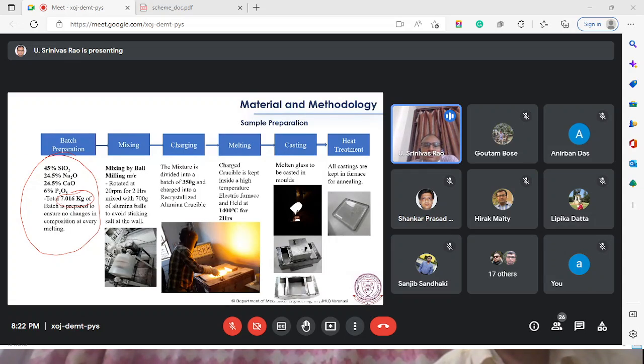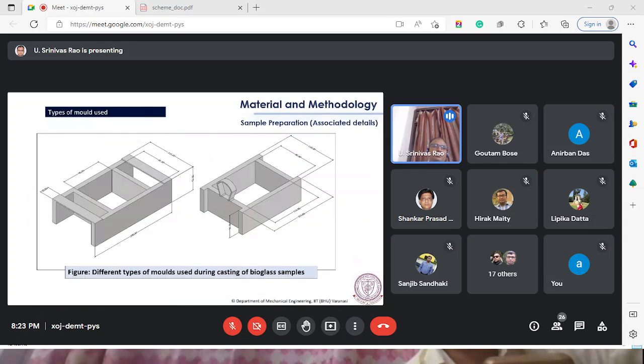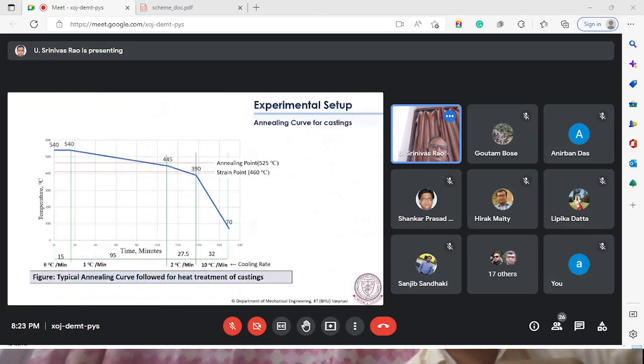Then it is divided into some batch size and kept in an alumina crucible, then charged in a high temperature electric furnace, and it is held at 1400 degrees centigrade for 2 hours. After this we obtain the glass, and that molten glass has to be cast into plates. Through some molding it is cast. Through this, glass specimens have been prepared, which will be used for different experimentation. So these are some details of the glass formation and how the glass property can be changed through annealing.